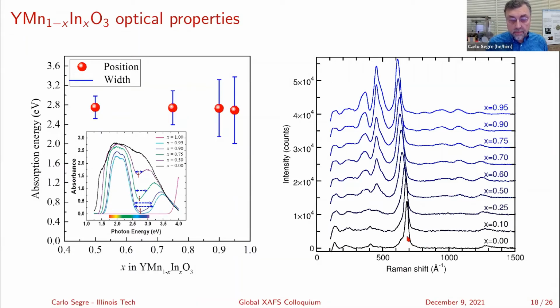which is all manganese, and x equals 0.95, which is mostly indium, you can see that there's a significant difference in the Raman spectra from x equals 0 to 0.95. And in the middle, you can see how basically these are just overlapping. So as you go up, you get more and more of the blue and less of the black.